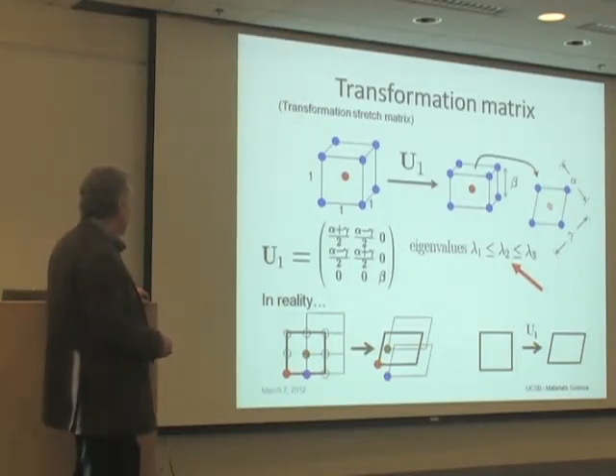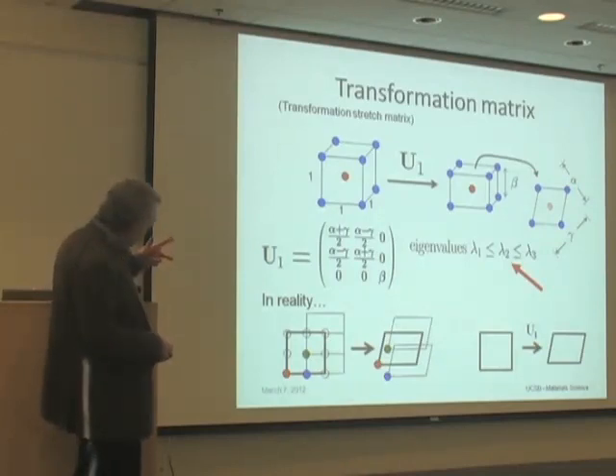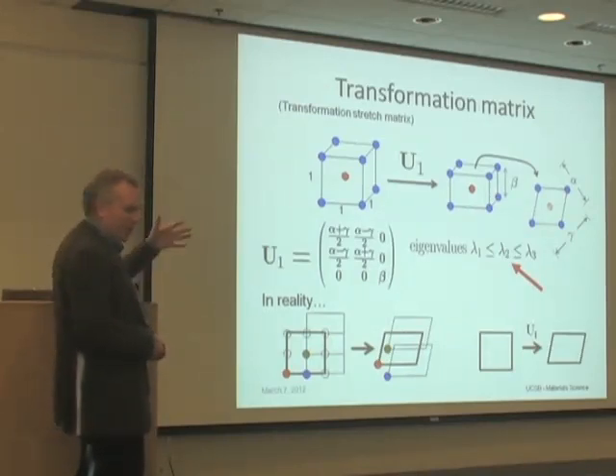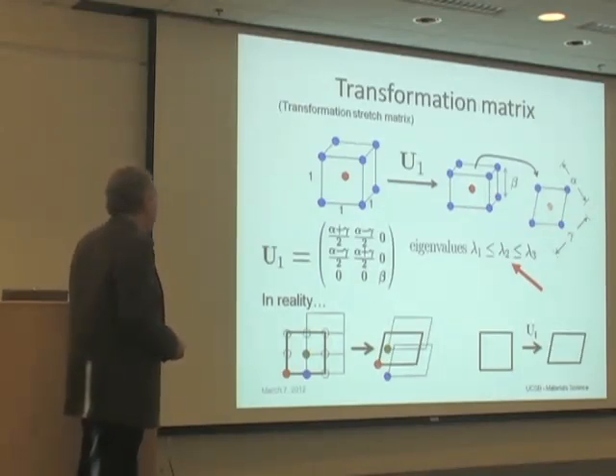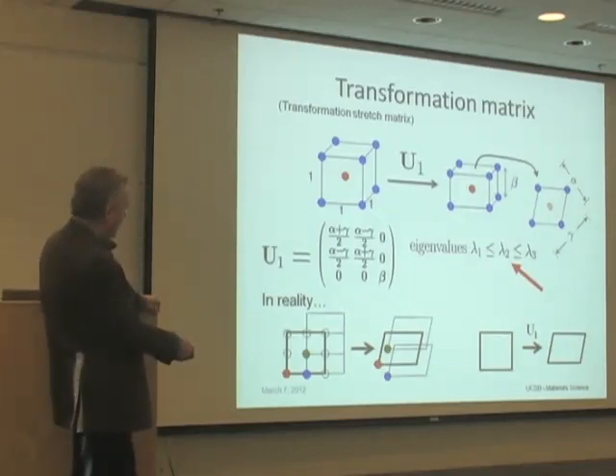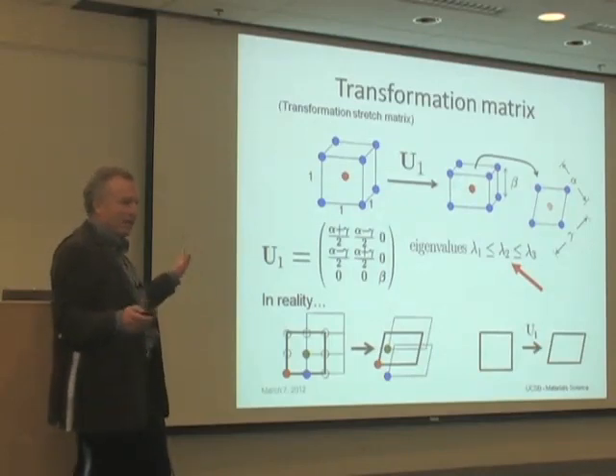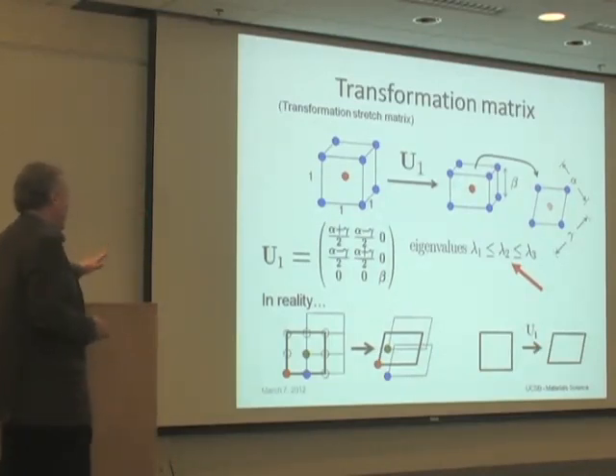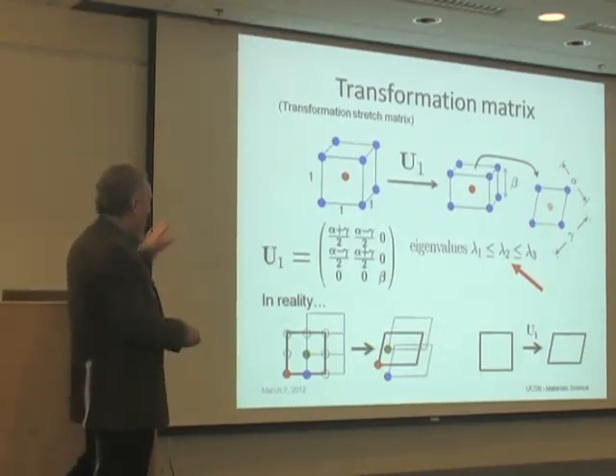And each of those Bravais lattices undergoes a distortion. In fact, it undergoes exactly the same linear transformation. It has to do that by periodicity. And it's that transformation, the middle eigenvalue of that transformation, which is important. That's what governs the long-range stress fields and things I'm discussing. So in reality, the textbook picture is too simple. But anyway, it's sort of a similar idea, and it's the middle eigenvalue that's important.